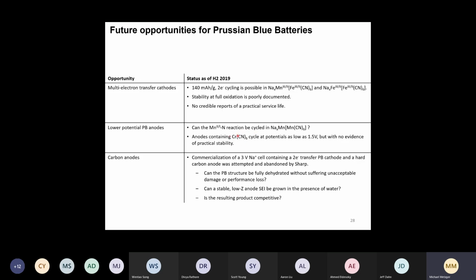I believe the chromium hexacyanochromate material is redox active at fairly low voltages. But also, you know, the stability is not very well documented for these materials when you go to such low voltage redox couples. And then one other thing you could do, of course, with these types of materials is you can pair them with a carbonaceous anode. So for example, a hard carbon anode, which is often used for sodium ion systems. And then you would get something around 3 volts for the cell voltage.